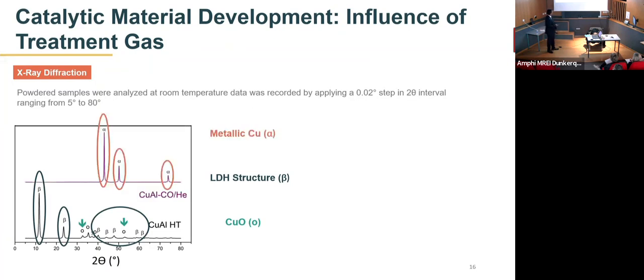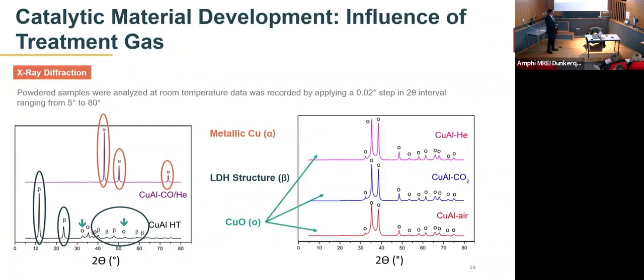Then upon treatment, for example, we started with carbon monoxide. We see that we had metallic copper on the surface, metallic copper in our carbon monoxide treated sample, which is again due to the highly reductive treatment of carbon monoxide diluted in helium. However, the other materials, that is the helium, air, and carbon dioxide treated samples, all showed us a similar diffractogram with crystalline peaks regarding the copper oxide species.